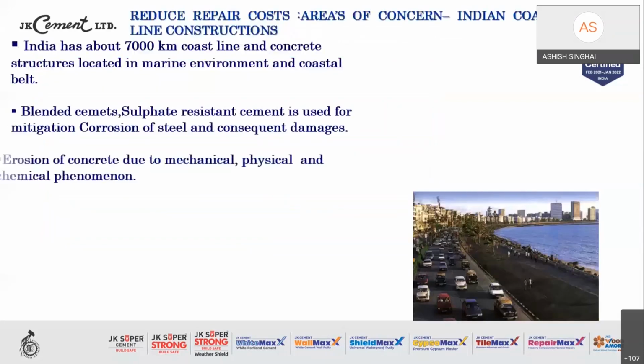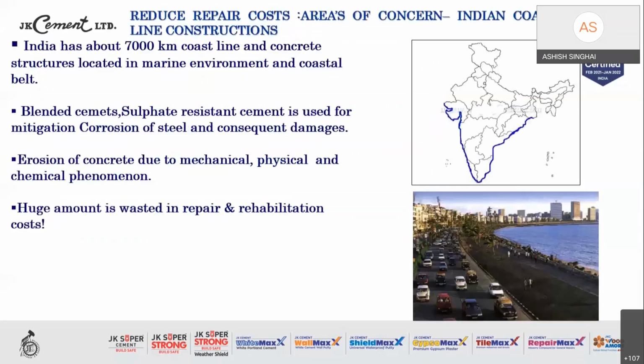India is typically blessed with 7,000 kilometers of coastal line. On the top right-hand side, you can see the blue dotted coastal line. It is in excess of 7,000 kilometers long. And as we all know, the coastal areas are always susceptible and vulnerable to chloride and sulfate attacks, so they will essentially harm your embedded steel. So we need to go for such types of cements for such areas wherein the impact of chloride attack, sulfate attack, as well as the alkali aggregate reaction can be minimized to a larger extent. For such constructions on these coastal lines, we always recommend Portland slag cement or Portland pozzolana cement.